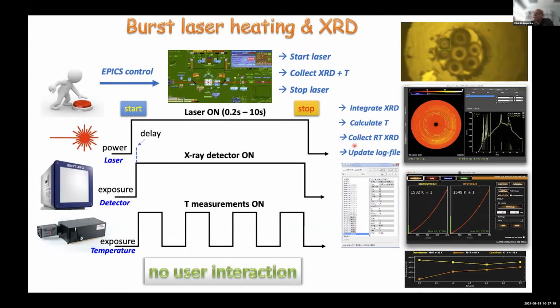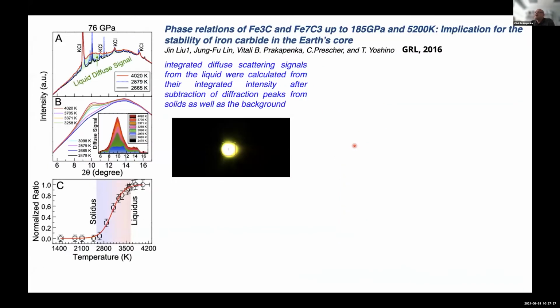And actually this technique helped us a lot during the pandemic, when we had remote operation, when the connection is not very stable. With this technique, Jeff, who was a graduate student working with APS-U, was able to do a quite difficult experiment on melting. You can see the diffraction pattern and the rising background, showing that the sample is molten. So he subtracted and plotted the integral versus the temperature, and you can see where the solidus and liquidus are.